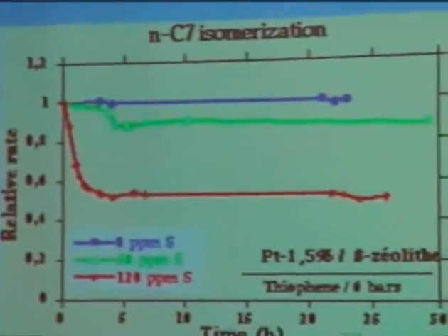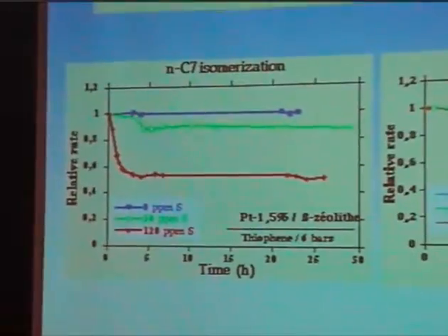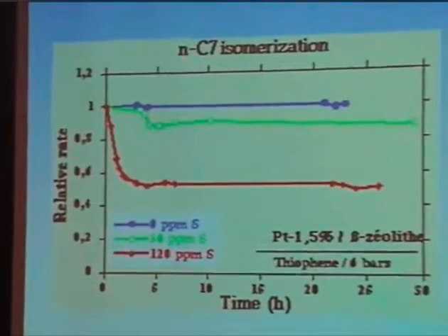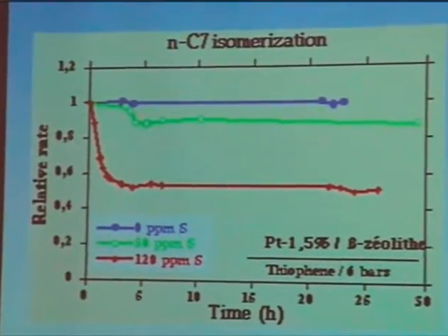And we have a third advantage, which is now the sulfur tolerance. Because these oxycarbides are more or less stabilized by the presence of carbon in the structure of the oxide, sulfur has difficulty to enter the structure. And not only that, sulfur molecules seem not to adsorb very well on these materials, because if you take thiophene, for instance, here is the example, we run without thiophene, 0 ppm of sulfur, and we have the rate 1. They are relative rates.